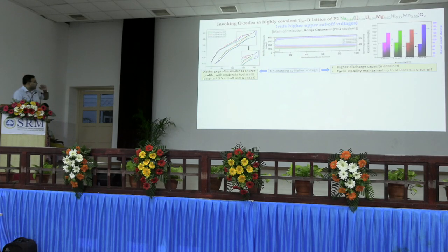Now again, I don't want to spend too much time, but with this high sodium containing layer transition metal oxide, the important point here was the increased covalency, and highly increased covalency, of the transition metal oxygen bond. If we understand a little about the oxygen redox, nobody understands too much of oxygen redox as of now, so it can be quite confusing. But we know that the higher the covalency, the better the stability, because it suppresses the oxygen-oxygen dimerization, and that is indeed what we see, though there are many surprises in this work, which we are trying to understand.